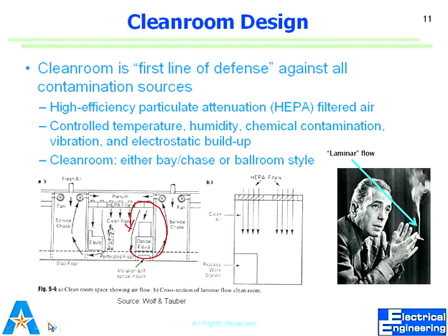What does humidity have to do with it? Photoresist essentially is a very fundamental process that we do. Photolithography, in which we apply photoresist on the wafer. The stickiness of resist, or its exposure, or its development, is highly impacted by humidity. Lithography, you'll see, I've seen it many times. Students would say, oh, I did lithography like 5 times and nothing worked. And I said, what was the humidity in the room? Every photoresist, every process has a humidity range that it will behave in. If we are above or below, it's not good.